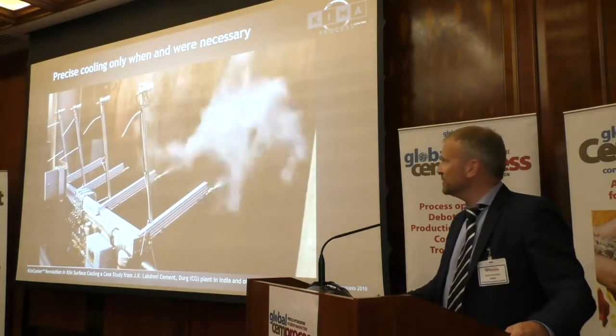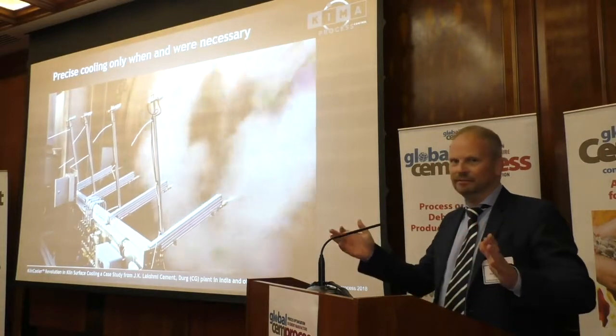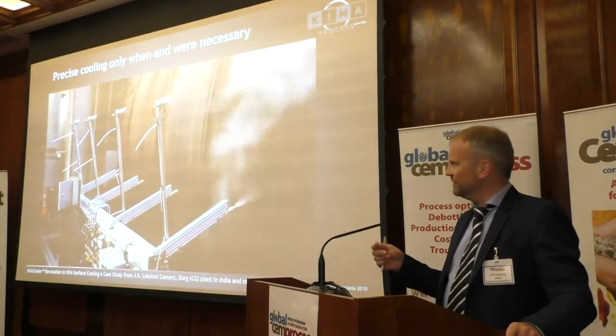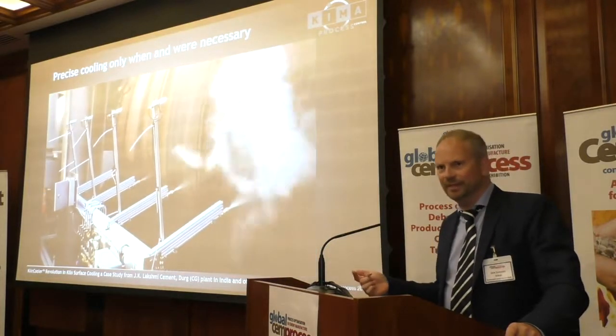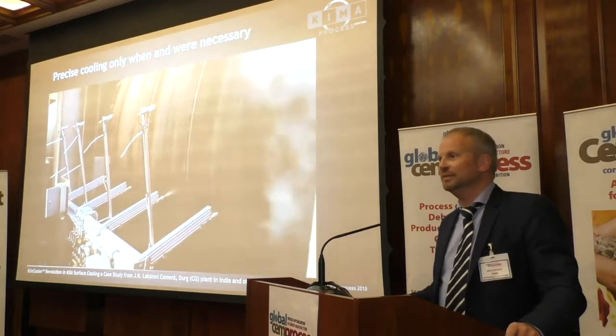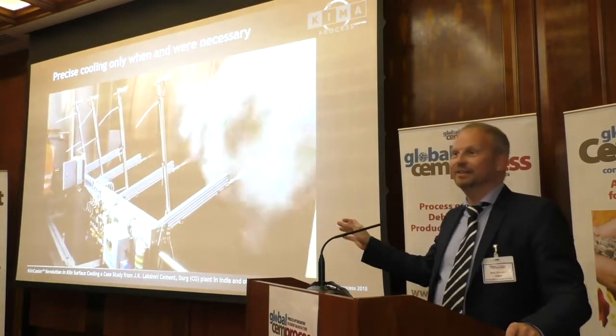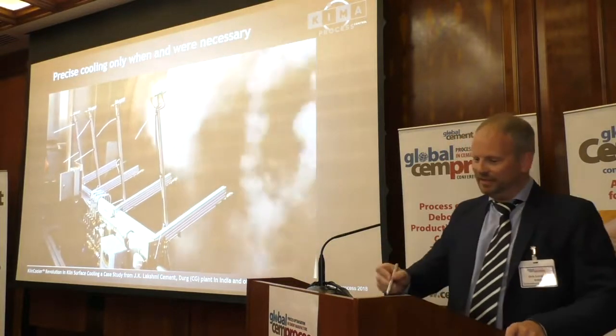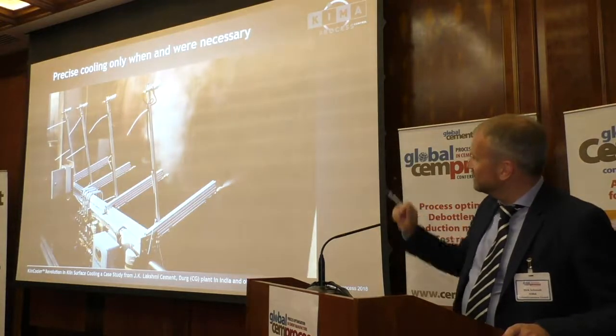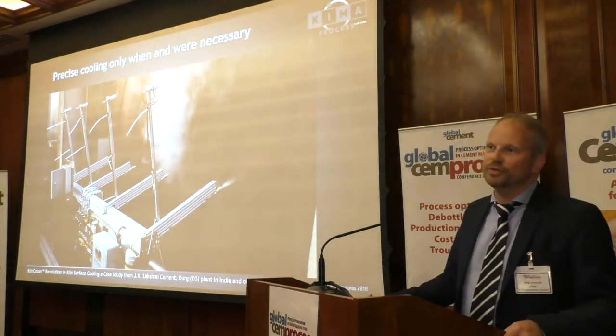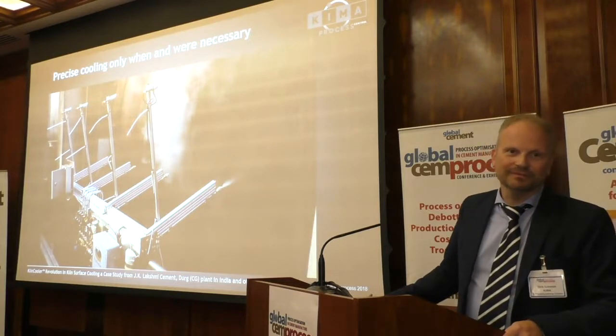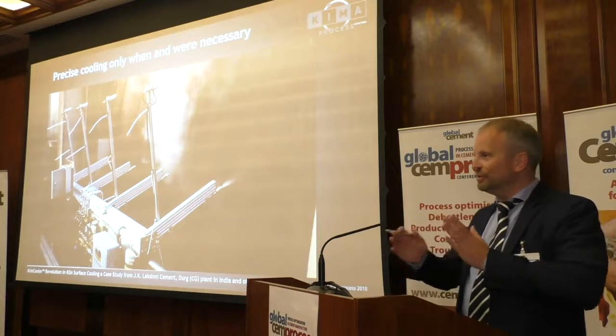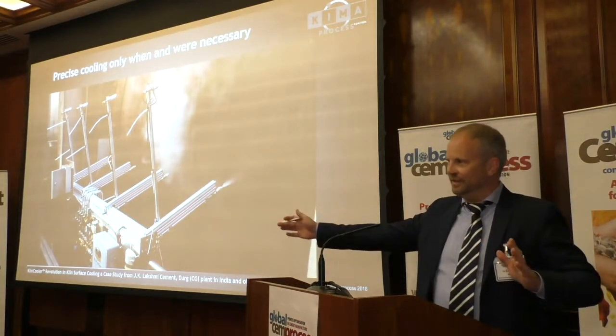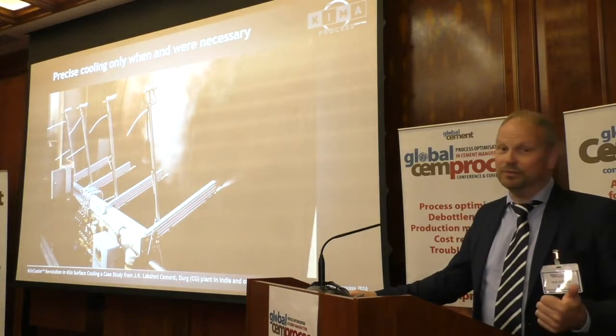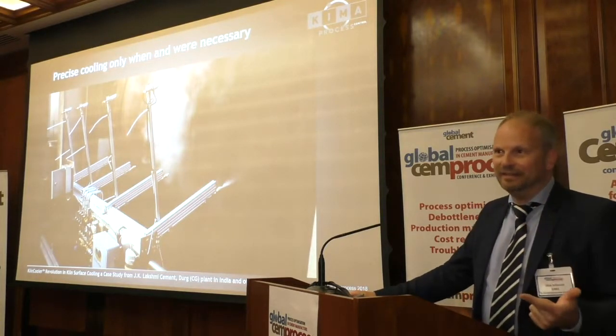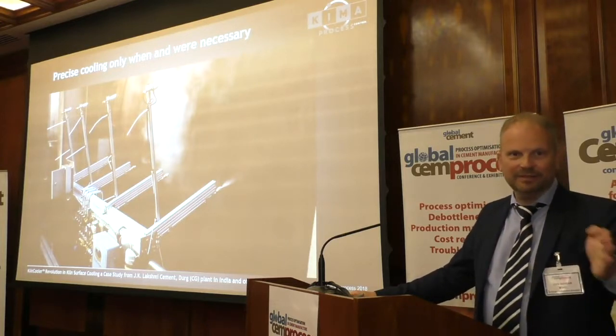So we designed the system in the meantime per meter. And let me drop this information also out because I think it's interesting. There is already the next generation. And this next generation of this KilnCooler spot hot system is worldwide patented, by the way. Underneath of this optical sensor which measures the temperature, there will be in future a laser distance measurement. With this laser distance measurement and a stationary cooler which is provided over the complete length of the kiln, you have the temperature profile, you don't need your thermoscanner anymore. And secondly, you will have the ovality of your kiln per half meter.